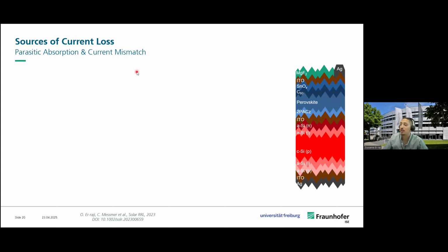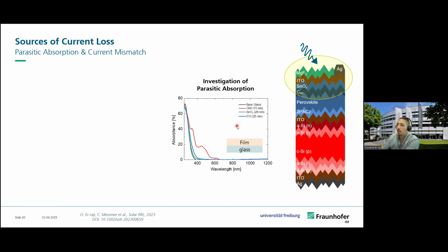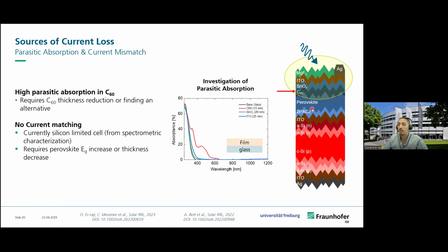So we will look first at parasitic absorption. As I said, we have the light which is incoming, and we want to reduce as much as possible light which is being absorbed in these layers. So we carried out UV-vis measurements, reflection and transmission, from which we can get the absorptance, and by comparing the different layers, C60, tin oxide, and ITO, we observe that the highest parasitic loss is in the C60 layer, which really takes away a lot of the useful light that can otherwise be effectively used by the perovskite. And in terms of the current mismatch, I don't show this here, but we carried out spectrometric analysis, which showed us that the cell that is currently limiting the device JSC is the silicon subcell.